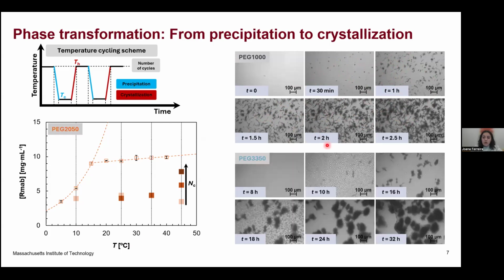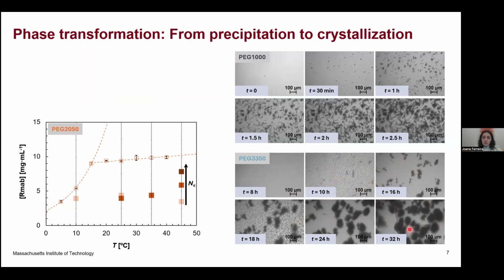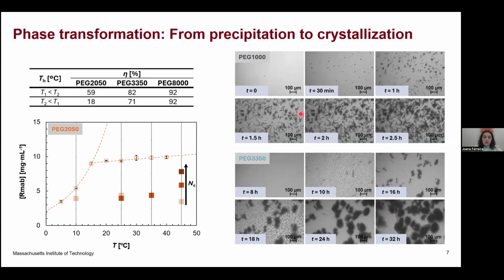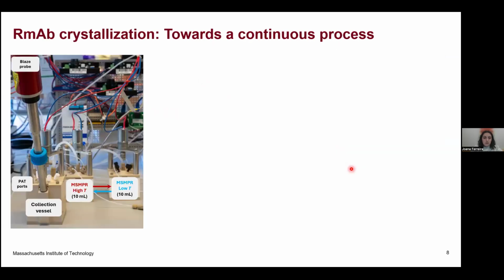And then for another PEG, it was also nice that through temperature cycling, we could really suppress the formation of the precipitants during the heating step. And then at the end, we could see some nice crystals. This process also gave us a good yield, especially looking at the high molecular weights of PEG, more than 70%, as in the case highlighted here in the slide.